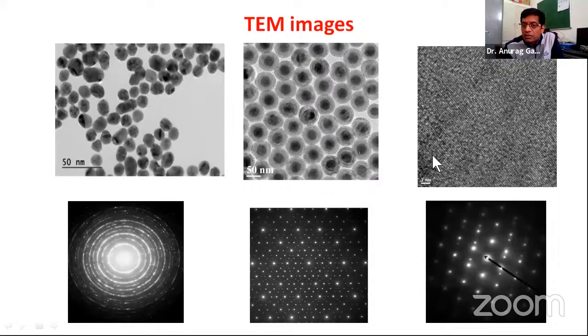You can see that the distance from one atomic plane to another is very small compared to this bar. So it is at angstrom level. You already know that the atomic plane distance d is in the order of 1 to 2 angstrom. That much is the range of the interplanar spacing. Even the interplanar spacing you can measure by HRTEM images, high resolution transmission electron microscope. So these atomic planes you can see with the help of transmission electron microscopy. This is the high resolution TEM image of a sample.